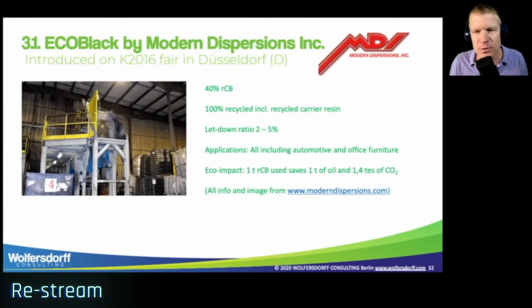And I want to give you a couple of showcases of companies that already have developed recovered carbon black master batches. I think the first company to have recovered carbon black in master batches was Modern Dispersions in the US. They introduced it at the Plastics Fair K 2016 in Düsseldorf. It is a 40% recovered carbon black master batch. It's also combined with recycled carrier resin, so it's a 100% recycled product. I think that's very good to have a 100% recycled product.